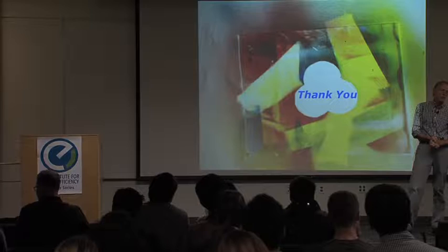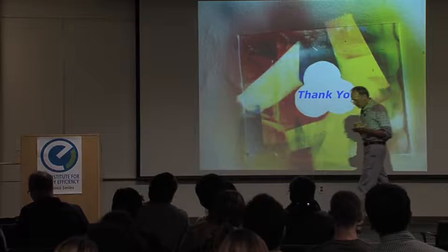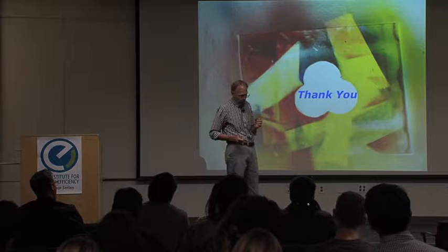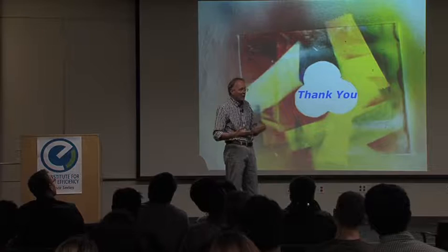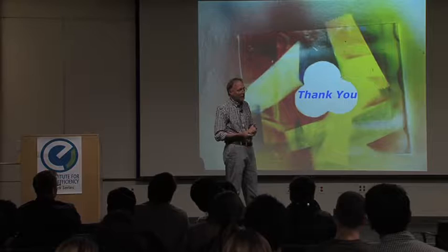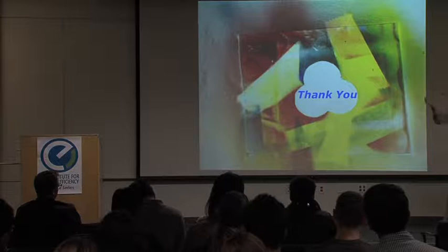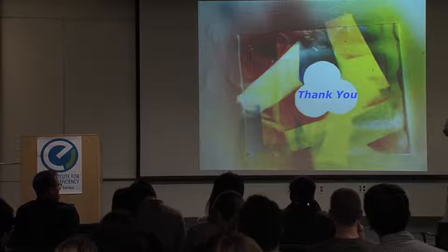In fact, the way we got onto this was we tried to make an organic soluble PEDOT. So we made PEDOT-C14. We put this tetradecyl chain on EDOT and polymerized it oxidatively. The student came in with a photograph of the oxidized form, and I told him he had something wrong because it was so clear. Now, unfortunately, those substituted EDOT polymers are very unstable in their neutral form to air oxidation compared to the ProDOTs.